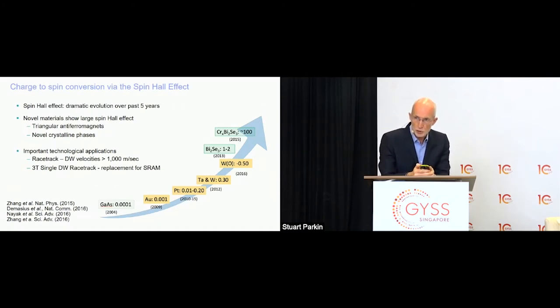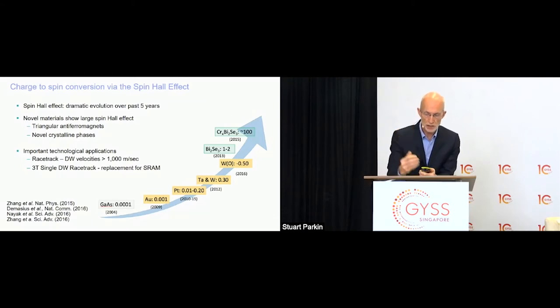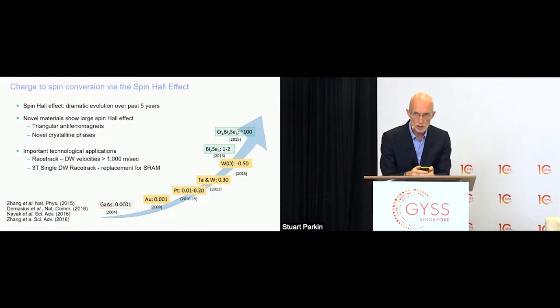But in the last few years, it's been demonstrated by ourselves and by others that the magnitude of these spin Hall angles, the efficiency of conversion of charge to spin current, can be extremely large, so that today we have materials where this efficiency is nearly one. In other words, every electron that passes through a material like platinum or other materials would be converted to a pure current of a single spin polarized electron. And this is extremely important technologically.